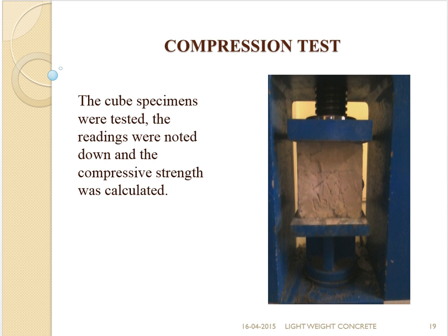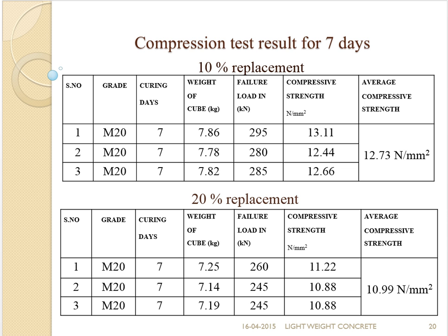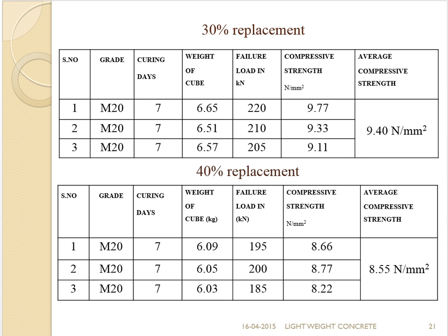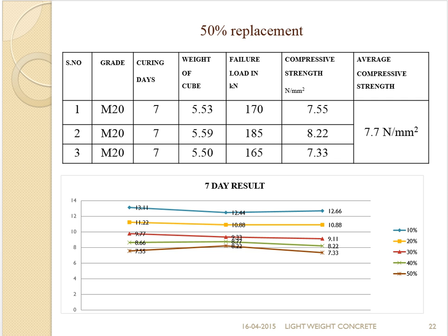The cube specimens were tested, the readings were noted, and the compressive strength was calculated. The compression test result for 7 days is that for 10% it is 12.73 Newton per mm square. For 20%, it is 10.99 Newton per mm square. For 30, it is 9.40. For 40, it is 8.55. For 50, it is 7.7 Newton per mm square. And the graph has been plotted for the 7-day result.